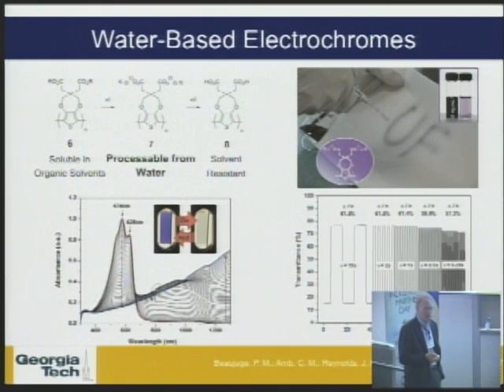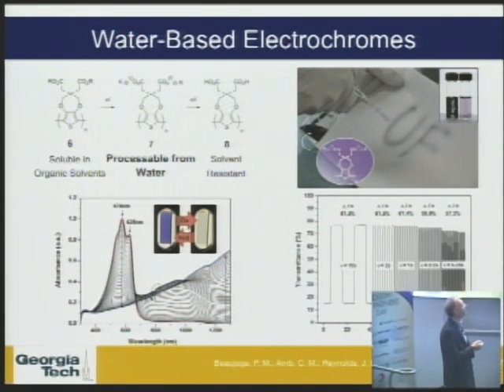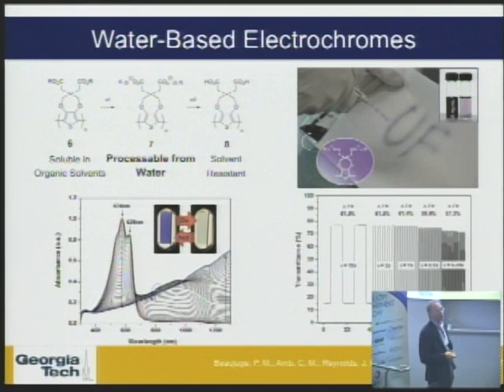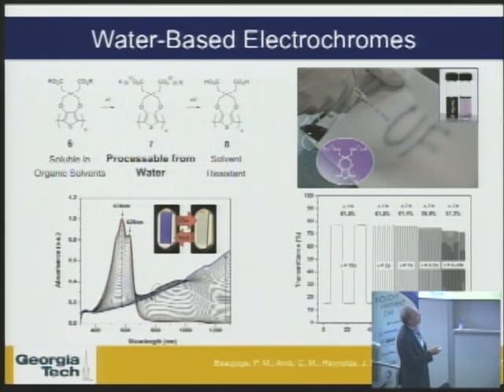Now, what organic chemists know is that carboxylic acids themselves are relatively water insoluble. And so the polymer here, after acidification, is resistant to both organic solvent and water to dissolution. And so we can switch this polymer electrochromically in an aqueous solution. I believe we're using sodium nitrate in water here as we go between the color state and the transmissive state. And again, you can see, looking at the transmittance changes, that we have good, strong transmittance changes with quarter-second switching.